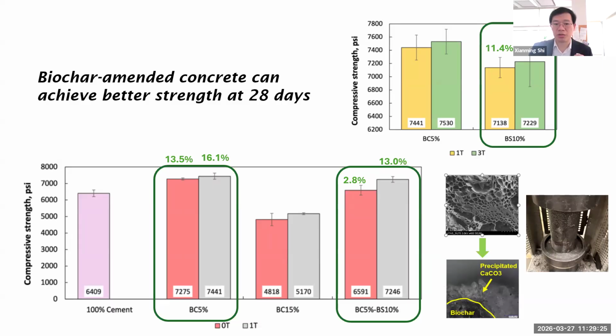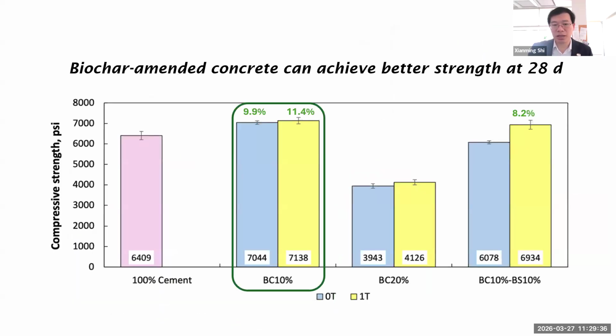That's very encouraging. Keep in mind, our intention is not to truly improve the strength. We just want to achieve at least comparable strength. The point is to reduce the carbon footprint of these mix designs. And continuing that, again, we went a little higher, 10%, still very good. And even 10% replacement of cement and 10% replacement of sand, they're very good. And now the different color actually shows the 0T basically means we didn't go through any sort of wet dry cycling, and 1T is one cycle wet dry to see the different levels of carbonate precipitation.